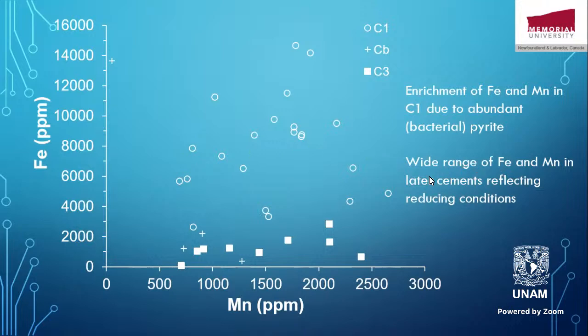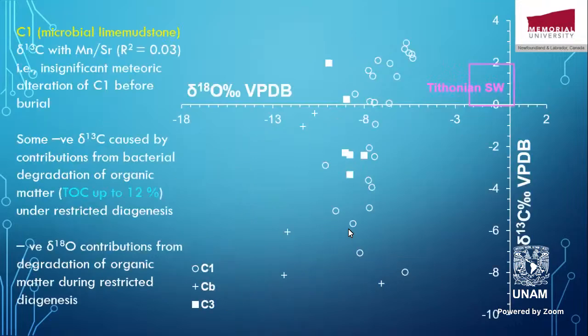And there is a wide range of manganese and iron, as I said, in the later cements, reflecting the reducing conditions, like here the C3 cement. Okay, the C1 is microbial lime mudstone, as we said. Here's the range of the Tithonian seawater from the best preserved carbonates. For the delta O18, it shifted towards more negative values. So there is some diagenesis there. We cannot say very, very low diagenesis. No, there is some diagenesis there.